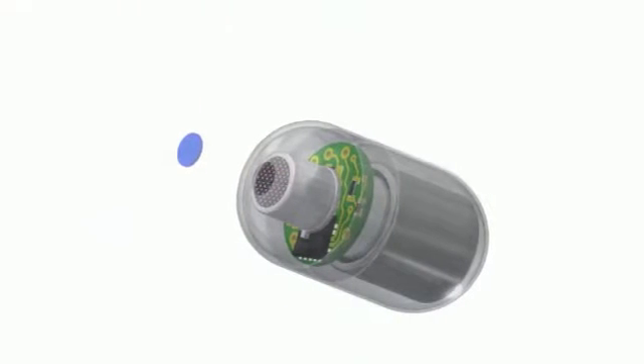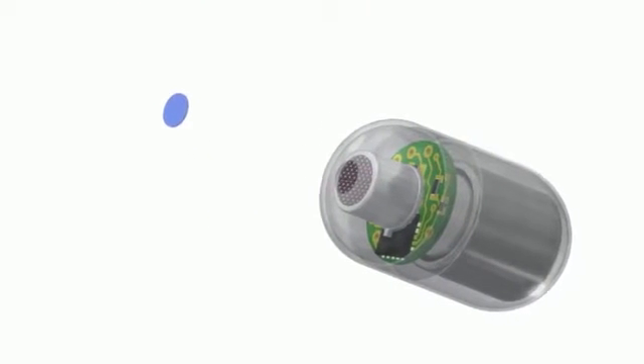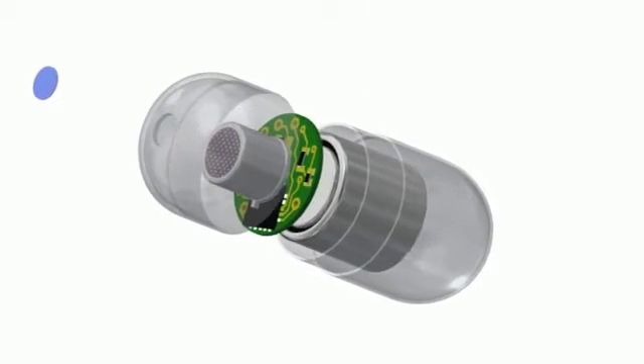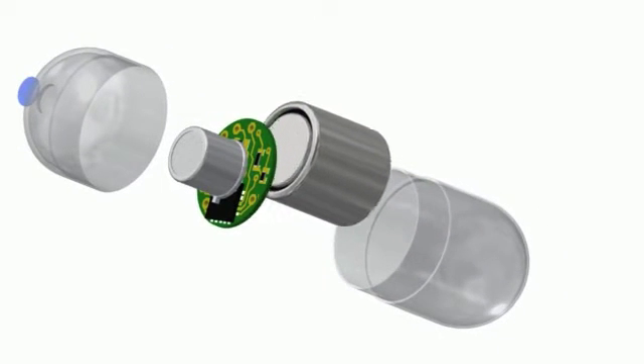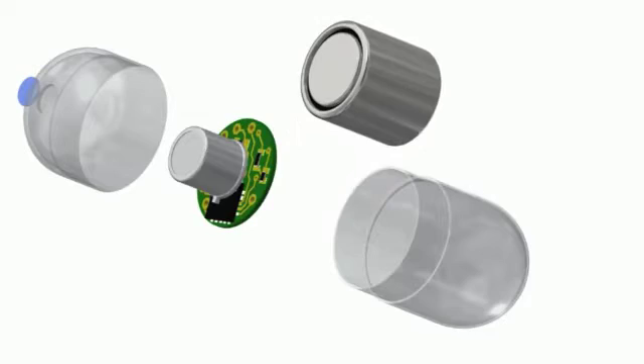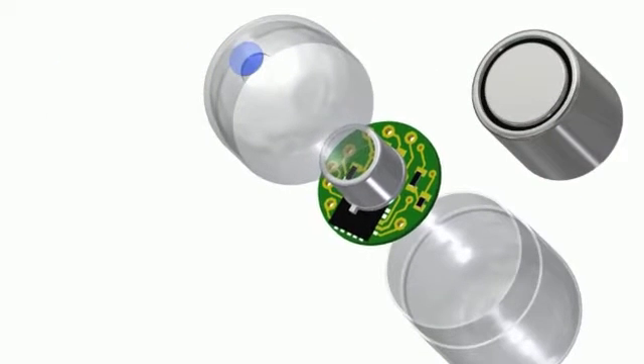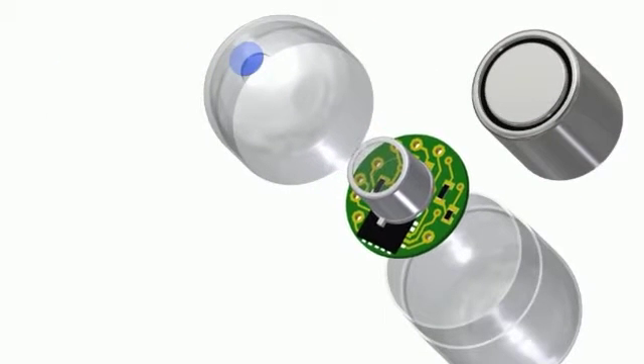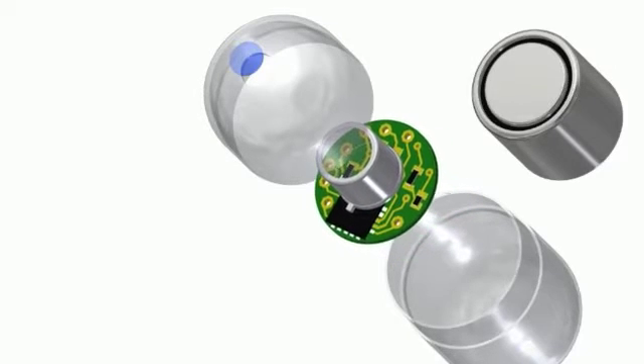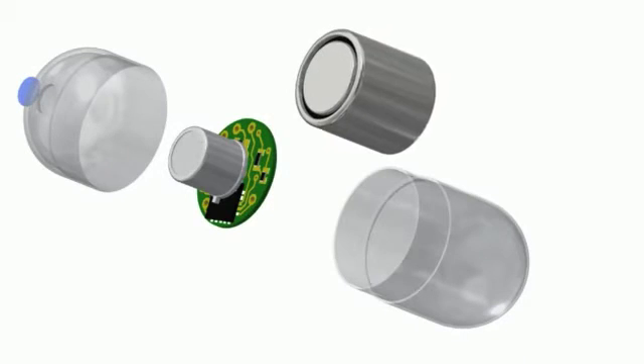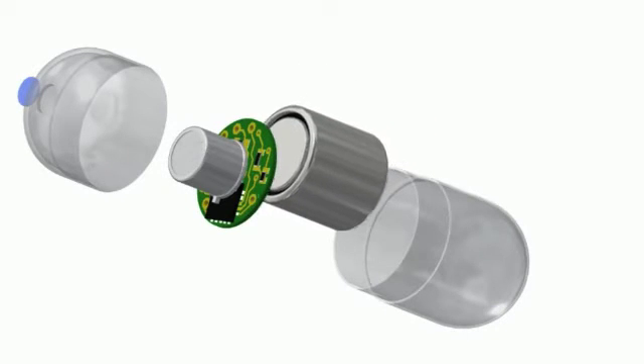We have developed the gas capsules used in the presented experiments, where each capsule is comprised of a gas sensor based on thermal conductivity which is sensitive to carbon dioxide, hydrogen and methane. It contains a polymer-based membrane at the front of the sensor made of rubbery polydimethylsiloxane with embedded nanoparticles to increase its permeability to the target gas molecules but not gut luminal liquid.